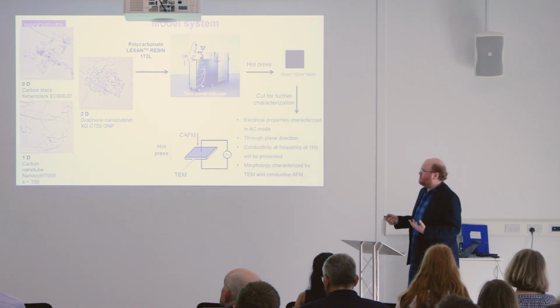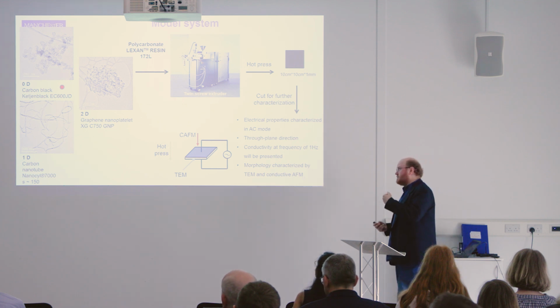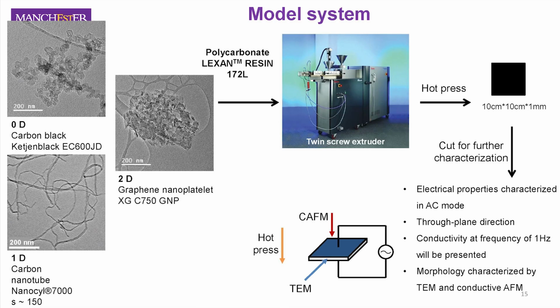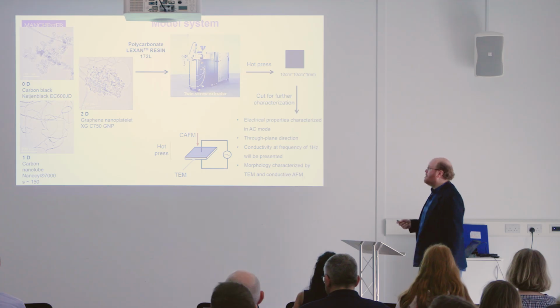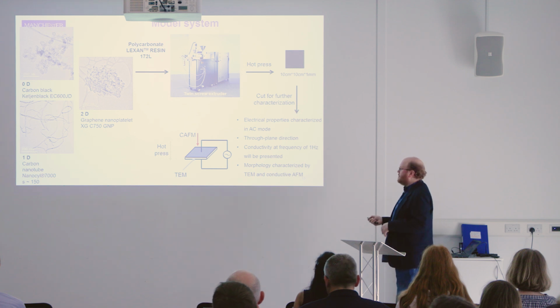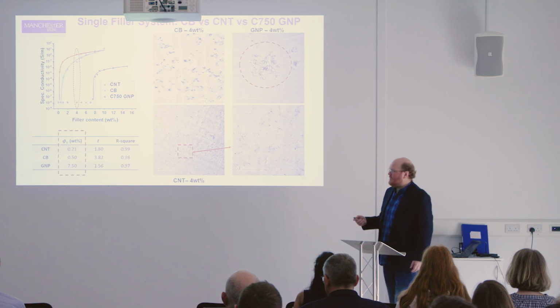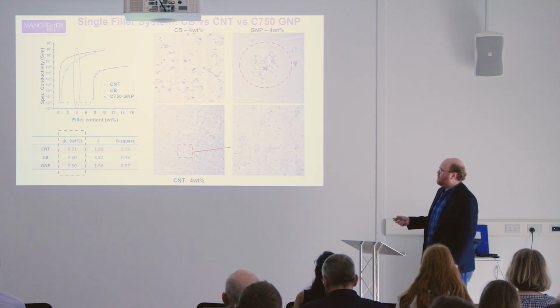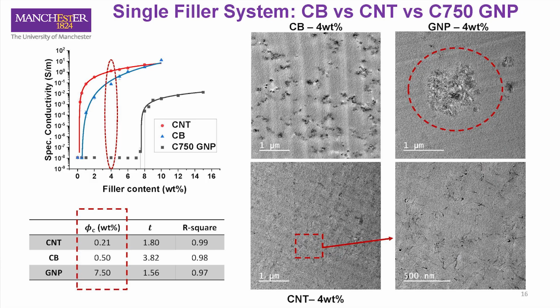The way we did this work is we took three model materials. We took a carbon black, Ketjenblack, which used to be made by Akzo and is now made by Nouryon. We took a graphene nanoplatelet from XG Sciences called C750. We took some carbon nanotubes from Nanocyl. We made individual composites out of these in polycarbonate, twin screw extruded them, hot pressed them, and then did a bunch of characterization to understand their conductivity. So we started off by making individual fillers, making these percolation curves for just the nanotubes, just the carbon black, or just the graphene.